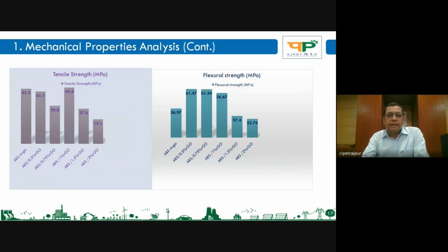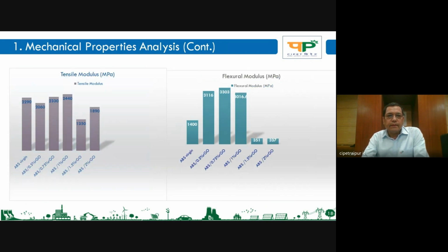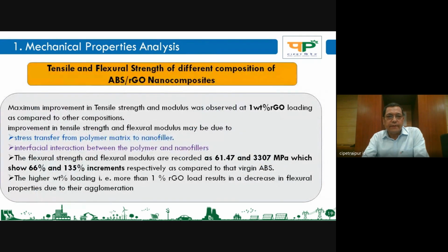So this is in graphical bar form. This is what our document has shown. This is the data sheet from which we get the different readings, as I have told earlier also. And there is very good enhancement in flexural strength as well as flexural modulus, 61.47 and 3307, showing around 66% and 135% increments. So this is a very good